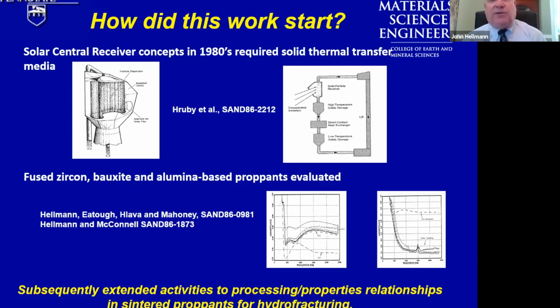Spherical ceramic particles on the sizes necessary here, something on the order of 1 millimeter in diameter, were not readily available in the ceramic industry at the time, with one potential exception. And that exception was a new family of materials that were being developed for the stimulation of gas and oil wells. These materials were known as proppants. They were manufactured from ceramic materials in a spherical form and were becoming available on the market in the quantities necessary for use in the solar central receiver. So we were able to demonstrate that technology, and it worked out well.